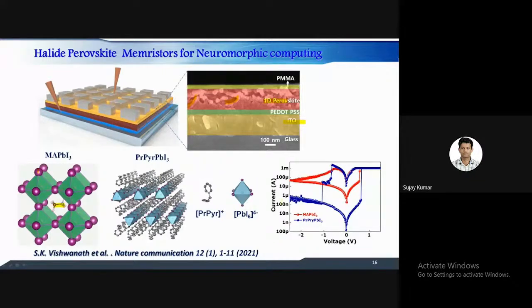When we compare the switching metrics for these two different materials, we saw that methyl ammonium lead iodide shows very leaky behavior compared to the low dimensional material. So we confirmed that low dimensional materials are very suitable for this particular switching to get a high on-off ratio.